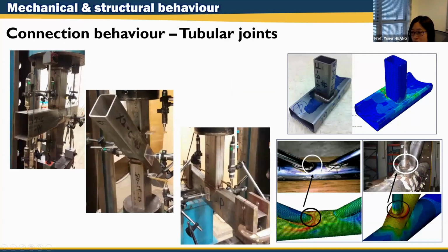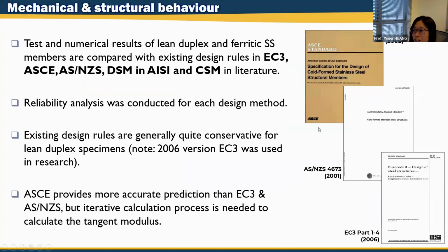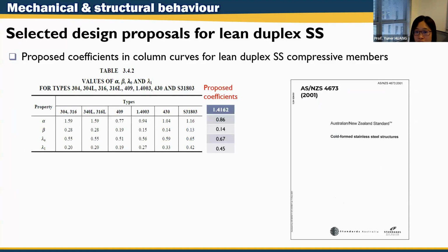And then for the tubular joint, we did a very similar thing, mainly to look at the lean duplex and ferritic stainless steel. And then our test and numerical results are compared with the existing international design guidelines, including the American, Australian and New Zealand, and Eurocode. And the conclusion is that all the international design guidelines are actually quite conservative for lean duplex specimens, which needs to improve. So that is why after our research, we proposed some new coefficients for lean duplex stainless steel.